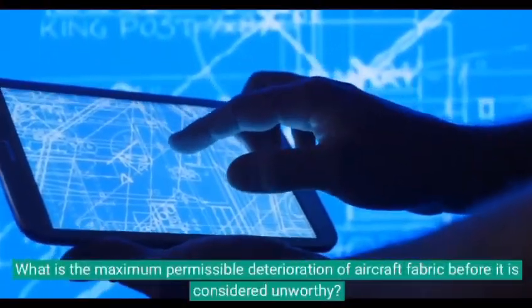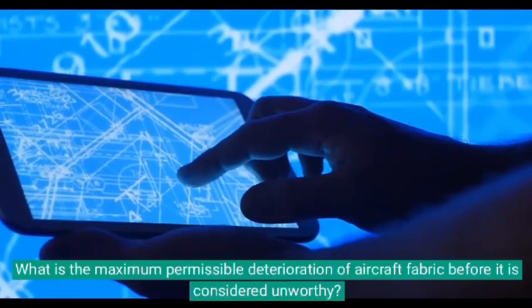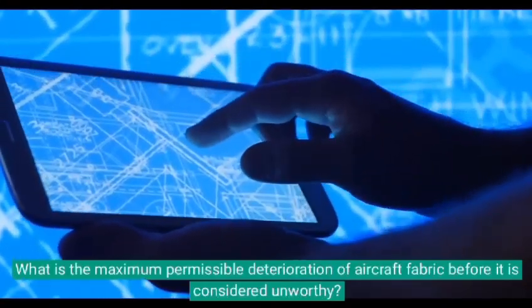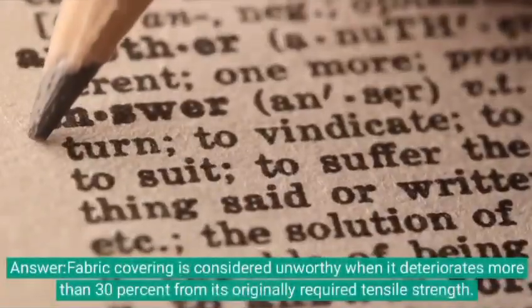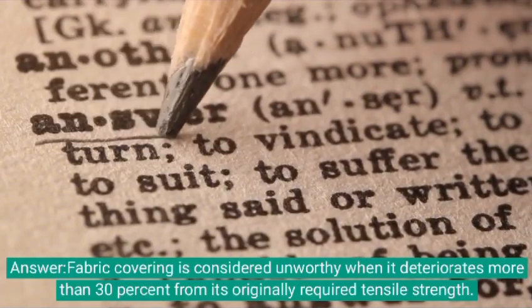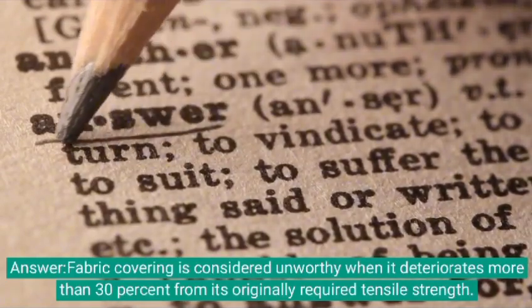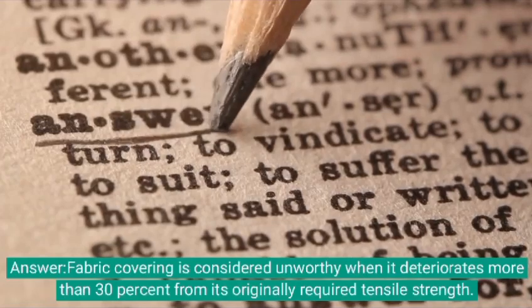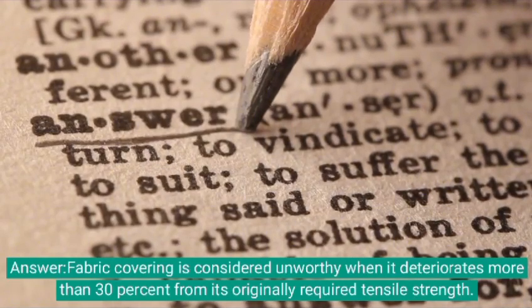What is the maximum permissible deterioration of aircraft fabric before it is considered unworthy? Answer. Fabric covering is considered unworthy when it deteriorates more than 30% from its originally required tensile strength.